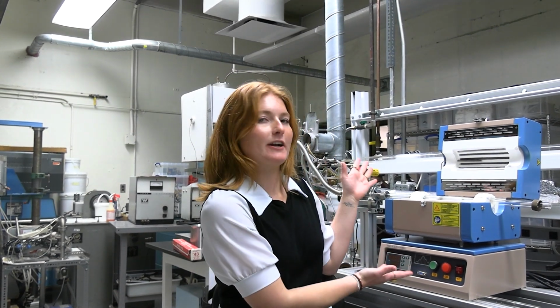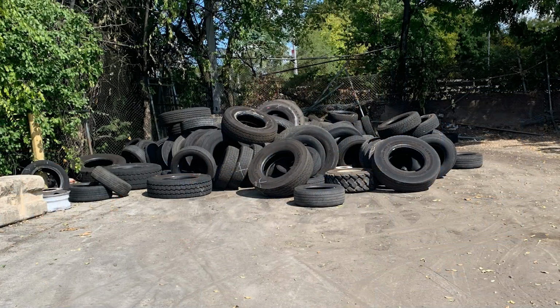Hard carbon is commercially available today, and it's been getting a lot of attention. The most common way to make hard carbon is to use biomass or carbon precursors and heat them at high temperatures, usually using a furnace like this. Biomass, such as wood or cellulose, is good for the environment because it comes from plants and trees. On the other hand, tires are bad for the environment, and they're difficult to dispose of. So we figured out a way to use the carbon precursors in the tires and make hard carbon. From rubber to the anode.